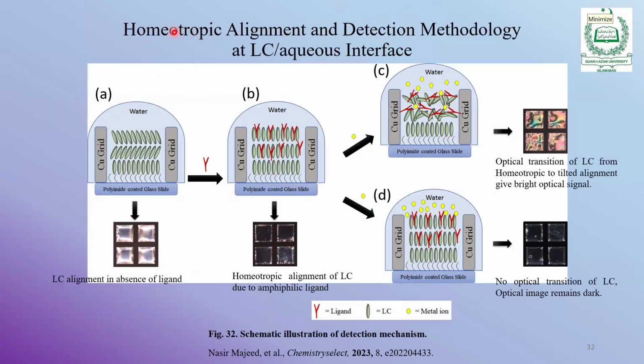Now, what is the mechanism? So, homeotropic alignment and detection methodology at the liquid crystal aqueous interface. In the absence of the ligand, as I told you before, when you have only liquid crystal, you will only see the bright texture. When you add water and it aligns the molecules, the liquid crystal sensor shows you the homeotropic alignment. So this bright image is going to the dark one.